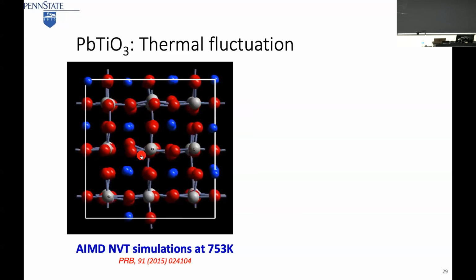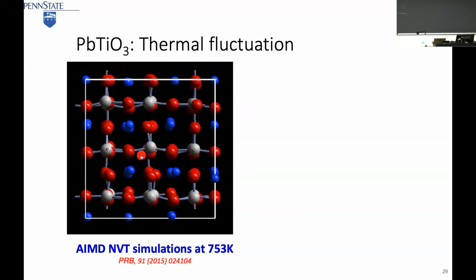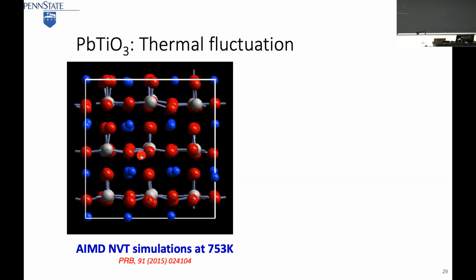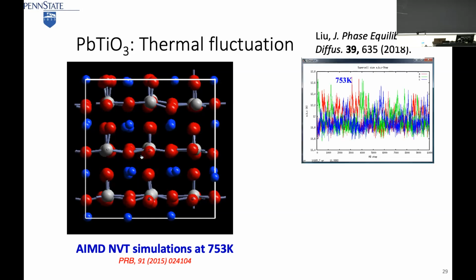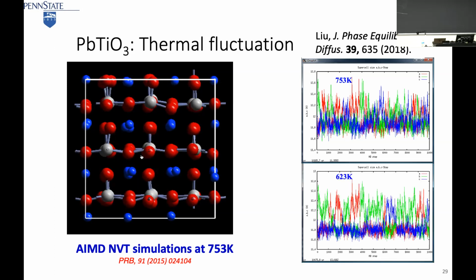Interesting that you don't see the blue atom sitting in the middle, right? It goes up and down, it goes sideways and so forth. So what it means is that the atom starts to move in this direction, then goes that way, goes this way, so it's upside down. It moves all the time. So that means at a high temperature, you see it move very fast. At low temperature, it moves slowly. The speed becomes slow. If you go to 0 Kelvin, it doesn't move anymore.